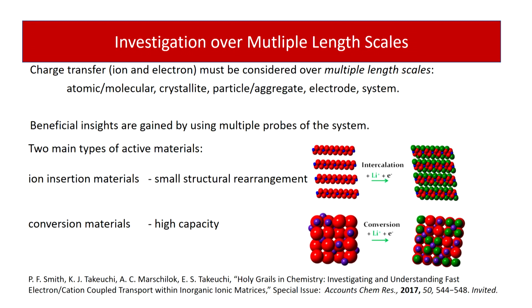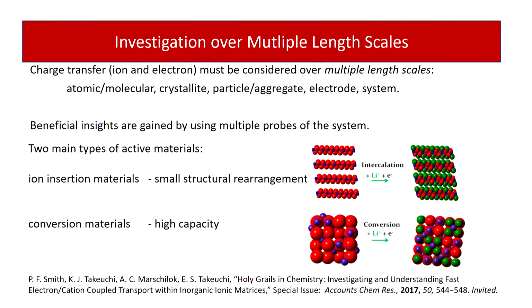What we find in very complex battery systems is that the atomic/molecular level, the crystallite, the particle, the aggregate, the electrode, all matter. They can all contribute to localized resistance that then impacts how the system functions. It impacts the loaded voltage relative to the open circuit voltage. And ultimately, that determines the amount of energy that we can realize from the battery. Not so much how much is in there, but how much we can actually realize. And by using multiple probes over various length scales, that's the path towards understanding what's really happening at these multiple length scales and then how those relate to the system.